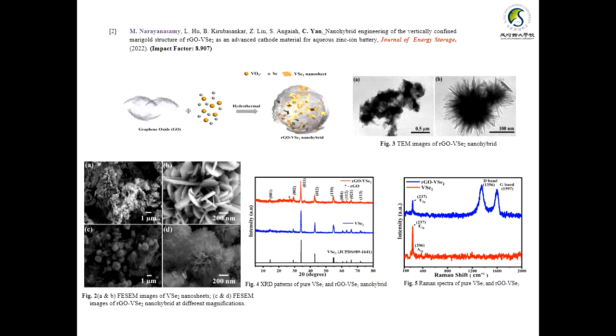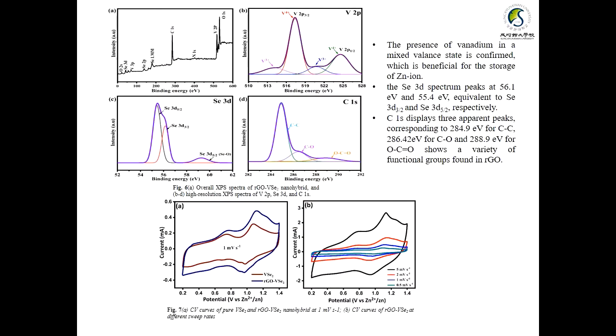Here in this SEM image you can clearly see that, when compared to the pure vanadium diselenide, upon addition of graphene oxide it is decorated uniformly as a marigold-like structure. In the XRD and Raman spectra we can see that the incorporation of reduced graphene oxide is present predominantly. In the Raman spectra, the D band and G band are present in the hybrid material. Further XPS analysis has been taken.